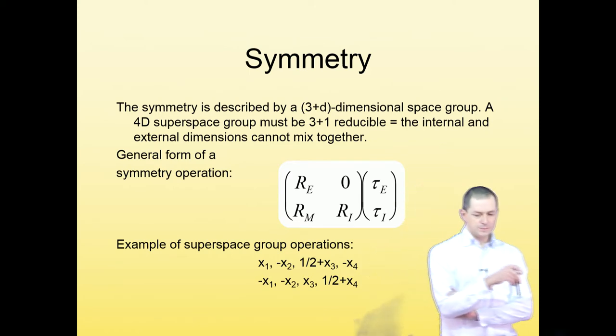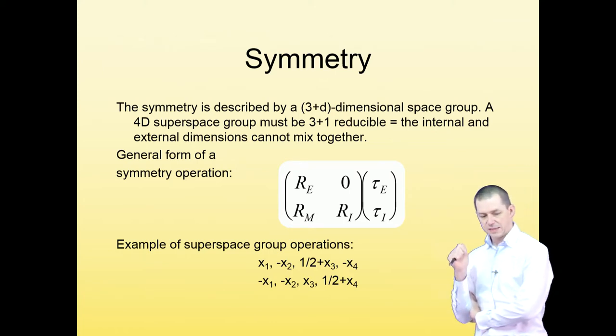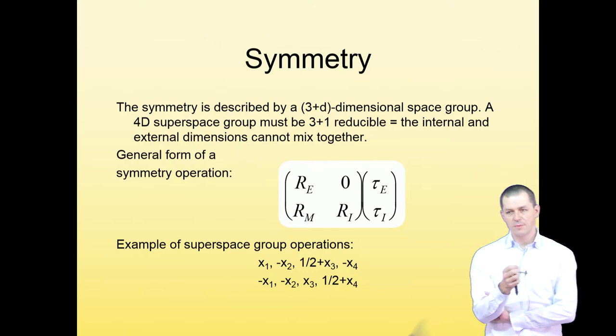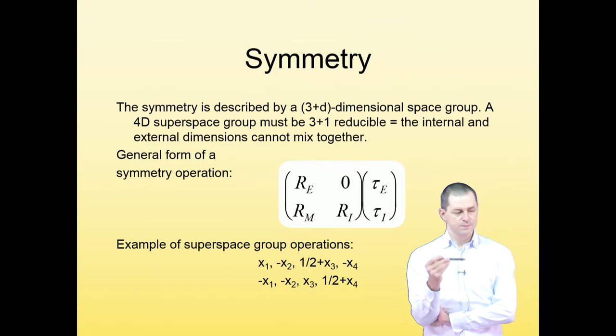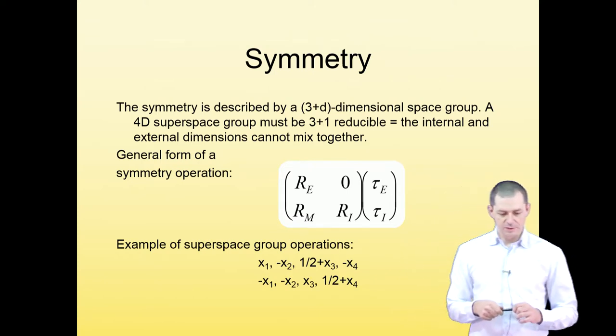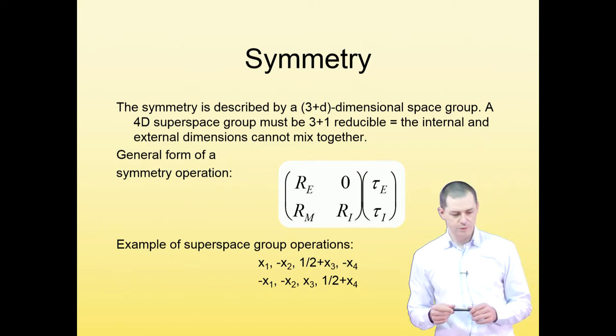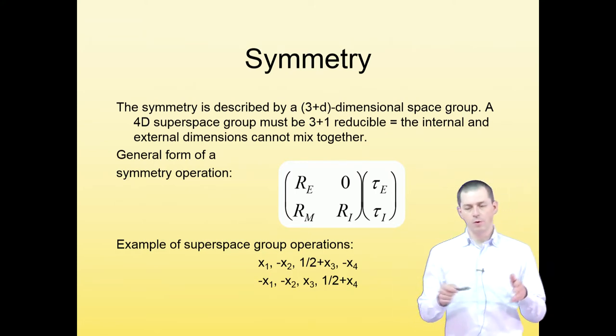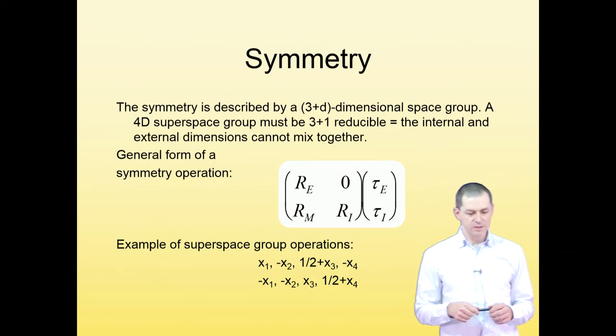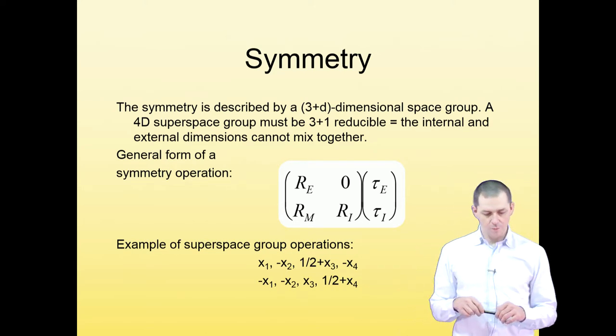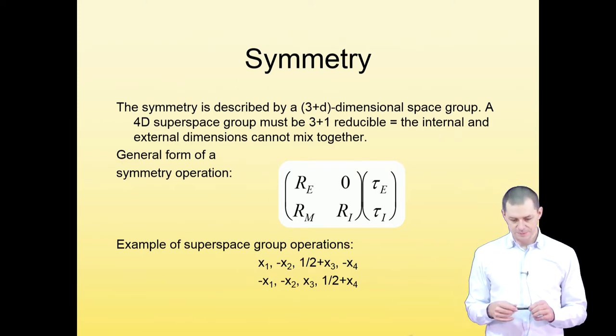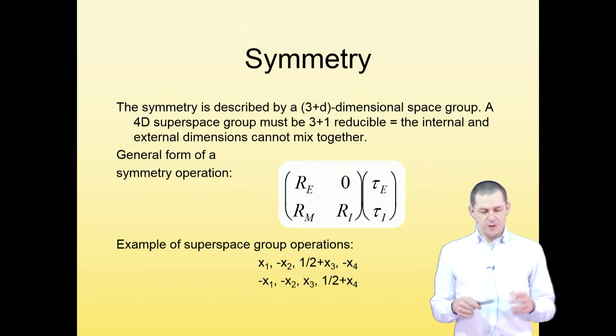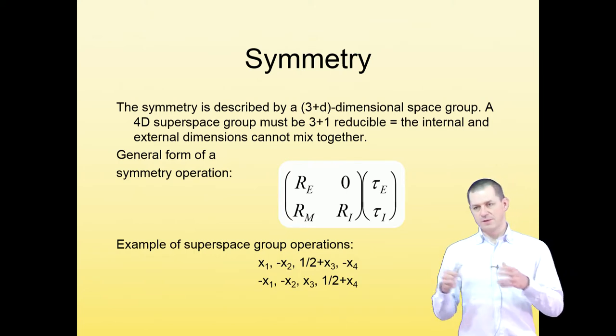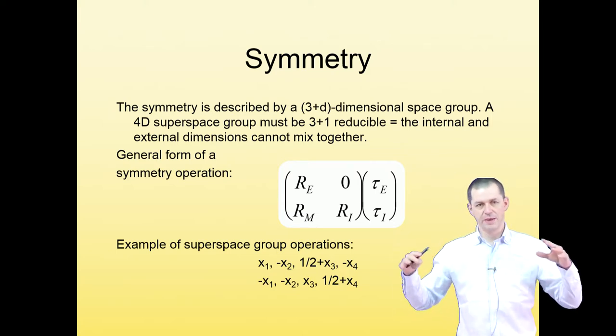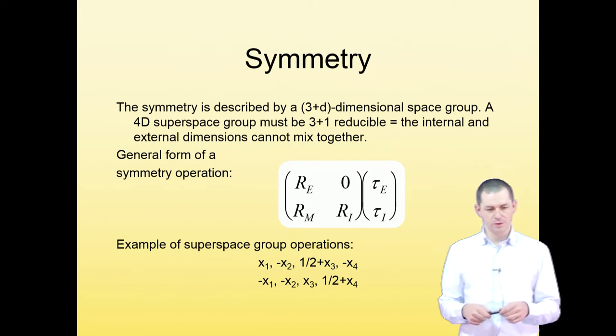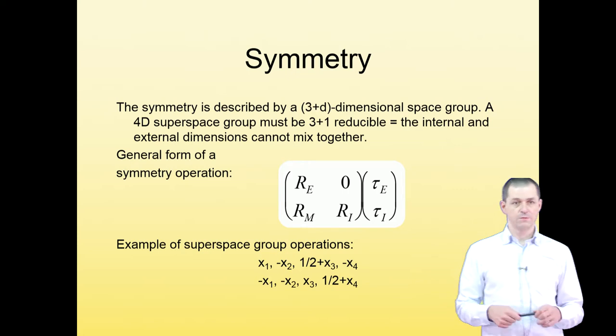A very important concept in the superspace description of modulated structures is the superspace symmetry. It's important for the same reason why symmetry is important for ordinary periodic structures. And the superspace embedding of modulated structures has its own symmetry, which is 4, 5 or 6 dimensional, depending on the dimension of the superspace, but it shares many properties with the symmetry of three-dimensional structures. Superspace symmetry must be 3+1 reducible. That is a mathematical expression for the fact that you cannot really mix the physical space and the additional mathematical construction, the additional dimension that we added to get the four-dimensional description.